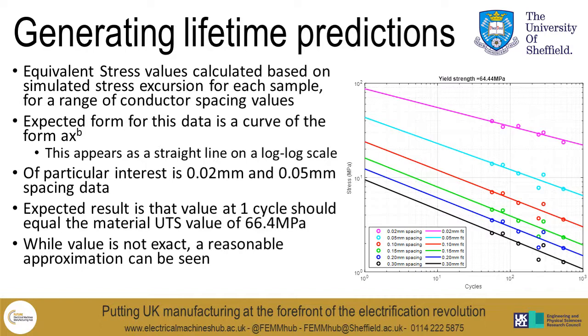Of particular interest is the 0.02 and 0.05 millimeter space data. This is particularly interesting because at a value of 1 cycle, you would expect that the curve should be equal to the ultimate tensile strength value of the material, which in this instance was 66.4 megapascals. While neither of these two curves exactly hit that value, they are both relatively close, and it's a reasonable approximation.